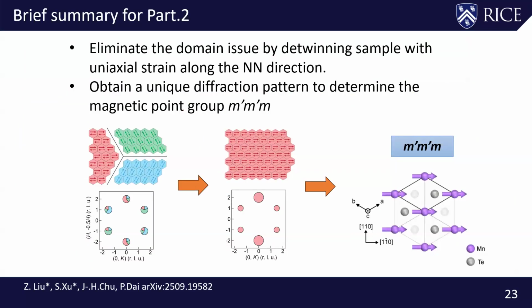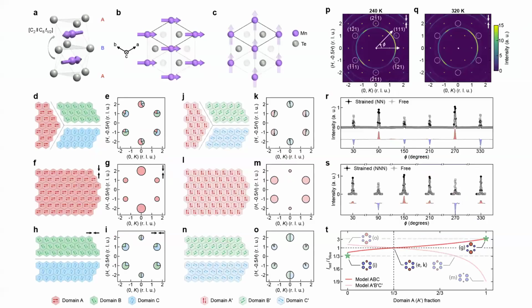If the magnetic structure is m'm'm, you should expect the intensity to change from this into this, because in both cases it doesn't matter what the spin direction is. The overall magnetic intensity is identical in both cases. But if you detwin it and it becomes this, then by looking at these 6 peaks and the intensity change, you should be able to see whether this magnetic structure is correct or the m'm'm magnetic structure is correct.